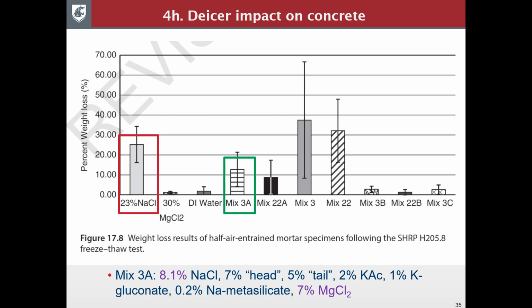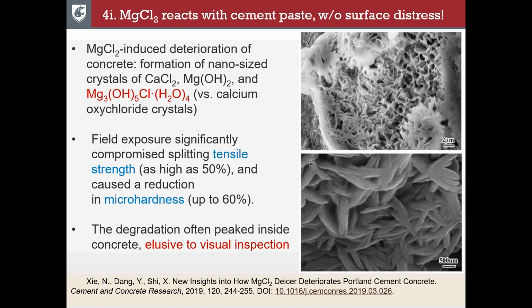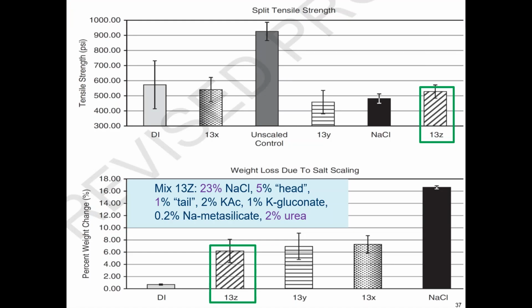However, at the time of that study, we didn't realize the potential problem with this magnesium chloride, because if we follow the SHARP test, as you can see, magnesium chloride was given the least mass loss. So the surface of the concrete was perfectly fine. However, in a more recent study, also from my group, we found there's some internal damage without surface distress or scaling. So in other words, the blending of salt brine with magnesium chloride should be carefully tested. One thing that would give us a better handle on the issue is, instead of relying on mass loss or scaling loss, we should also test tensile strength or compressive strength.